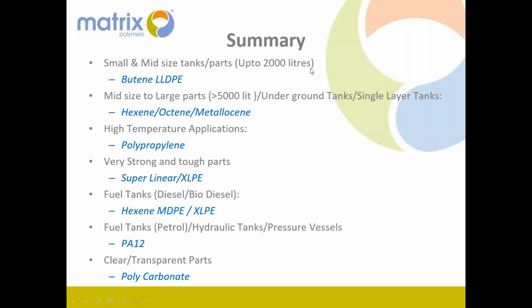Small and mid-sized tanks up to 2000 liters, butene LLDPE is the best material, nothing to beat that. Mid-sized to large parts, 5000 liter tanks and above, underground tanks, single layer tanks, you will consider hexene, octene, metallocene. High temperature applications, polypropylene. Very strong and tough parts, you need superlinear, the very high density, or XLPE. Fuel tanks, diesel, biodiesel, hexene, MDPE or XLPE. Fuel tanks, petrol or hydraulic tanks, pressure vessels, PA12 nylon. Clear transparent parts, polycarbonate. So this is the summary of the topic of materials. Choice is yours.